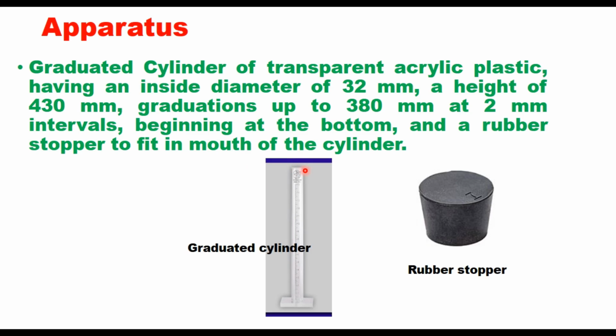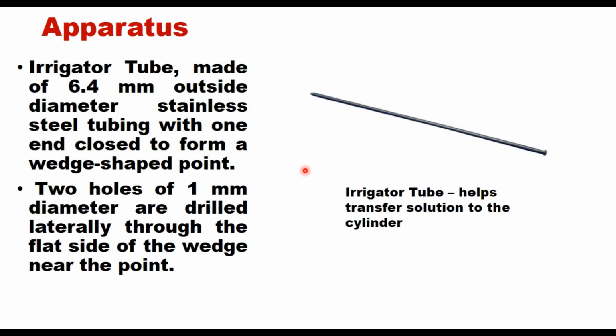of this cylinder. The cylinders used here are unique. Instead of volumetric divisions, they have graduations every 2 mm. An irrigator tube, which is made of 6.4 mm outside diameter stainless steel with one end closed to form a wedge-shaped point, and two holes of 1 mm diameter are drilled laterally through the flat side of this wedge near the point. And this tube helps transfer solution to the cylinder.